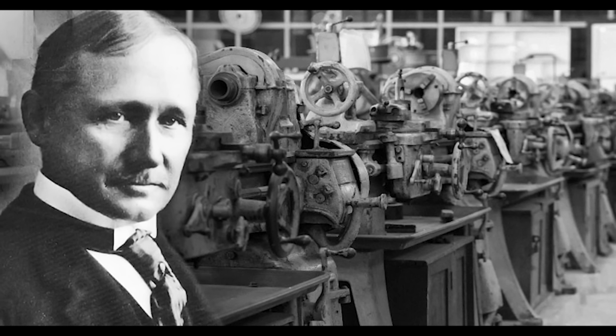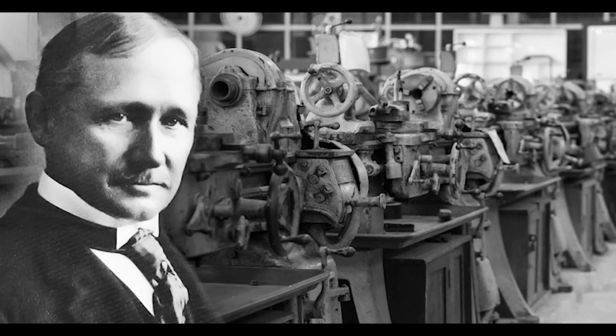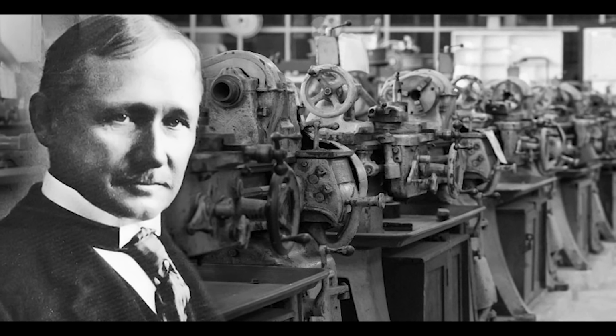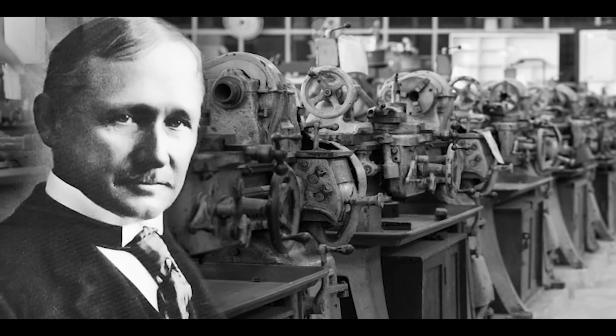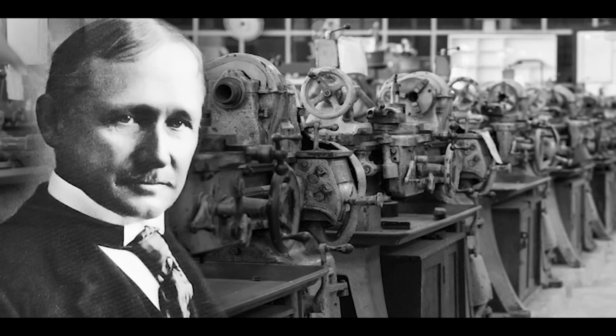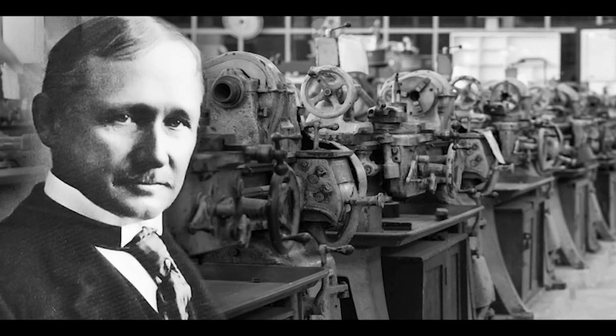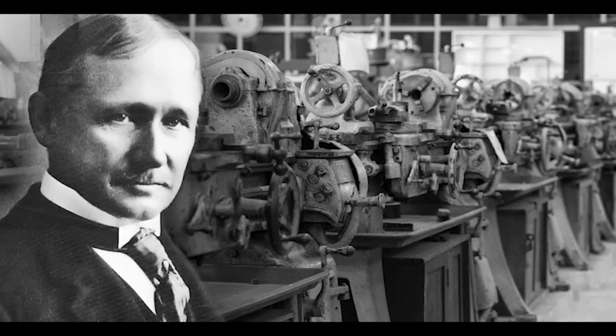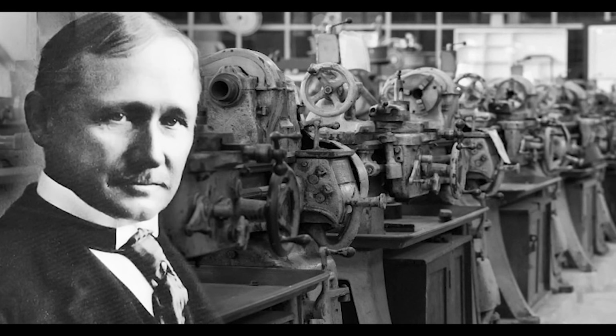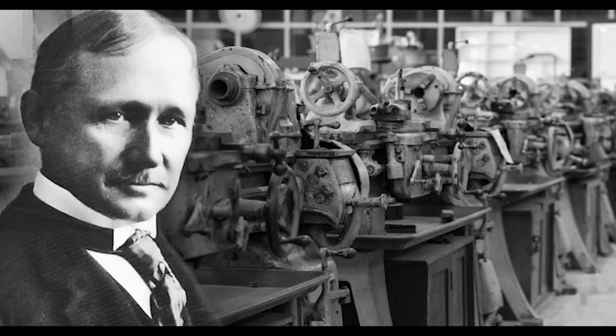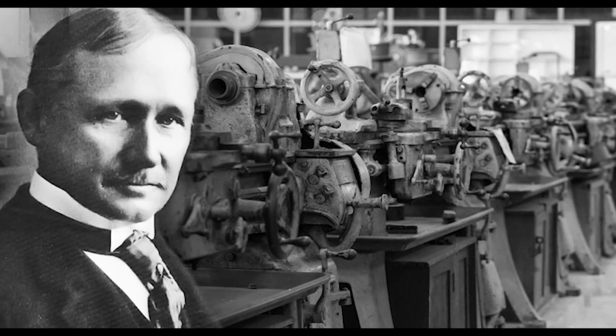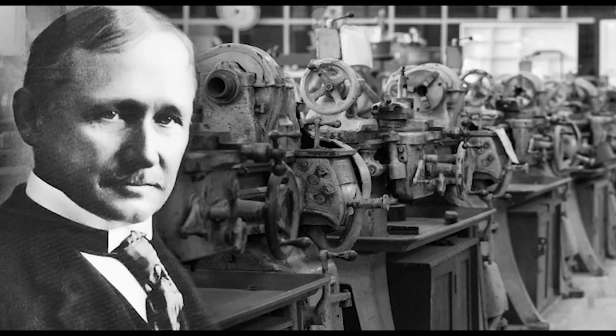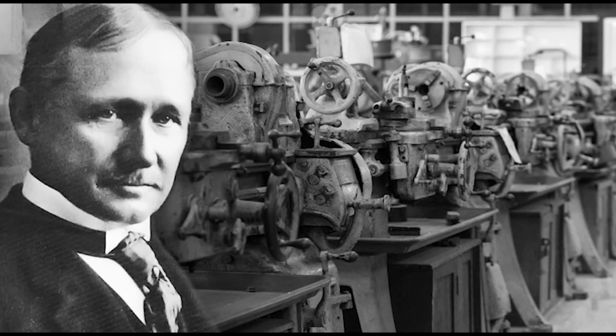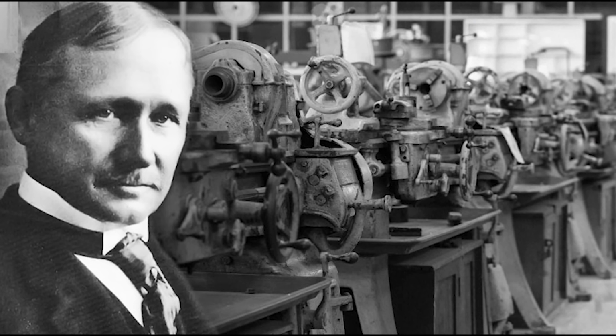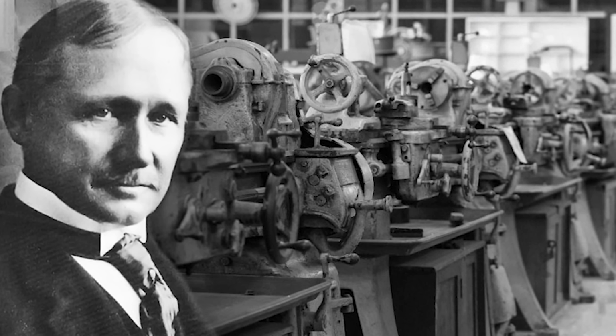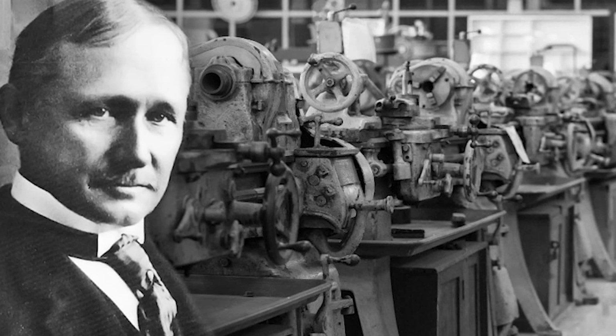The audience watched in stunned silence as metal peeled away in blue-hot spirals, while the cutting edge maintained perfect geometry. European metallurgical theory predicted catastrophic failure, but American experimentation had discovered operating conditions where theory was incomplete. The visual impact was overwhelming. Observers who had dismissed Taylor's work as dangerous American overconfidence were witnessing cutting performance that violated fundamental assumptions about metallurgical limitations.